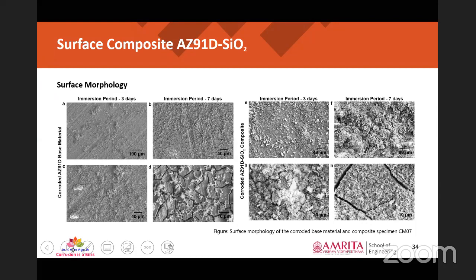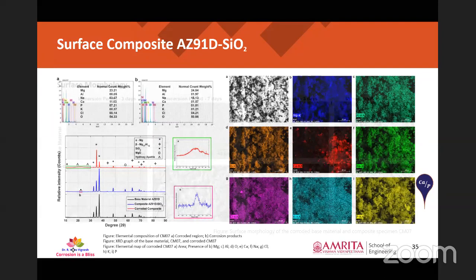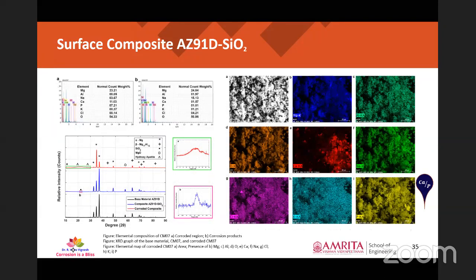So to analyze the corrosion products, again we have gone for elemental mapping, XRD analysis and EDS too. So the EDS analysis has given us an idea that the calcium to phosphorus ratio is around 1.65. Which means there is the formation of calcium hydroxyapatite crystals or calcium magnesium phosphate crystals in the material after 7 days of immersion. And XRD analysis also confirms the presence of hydroxyapatite in the corrosion products of the composite material.